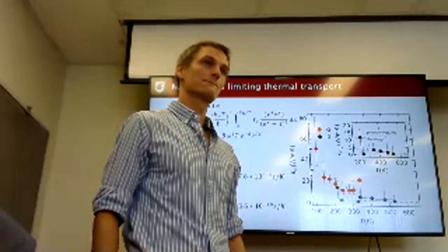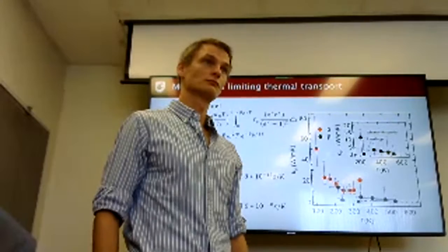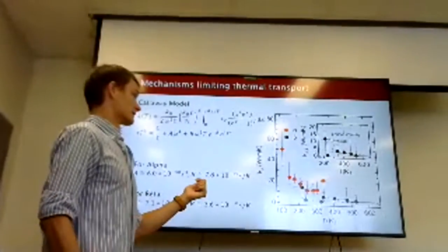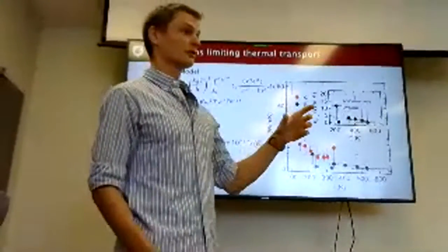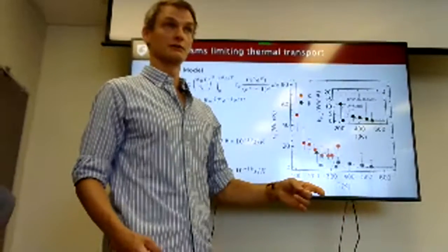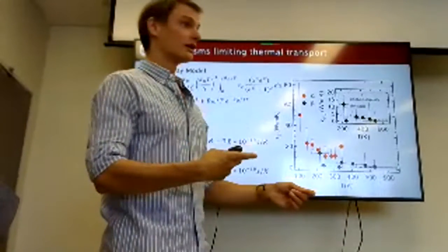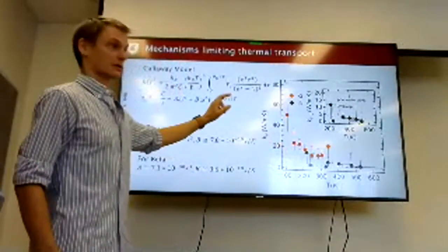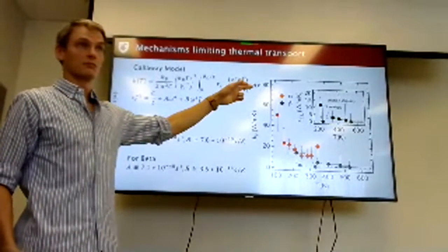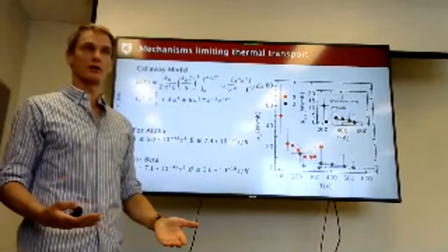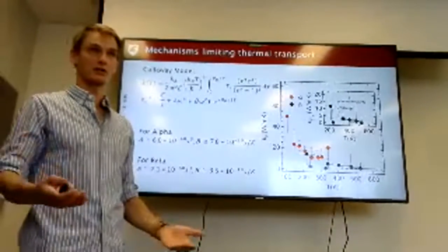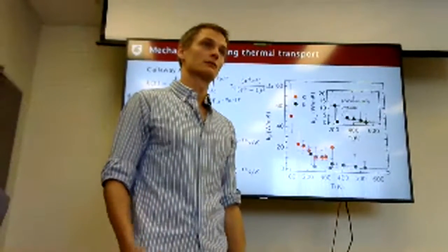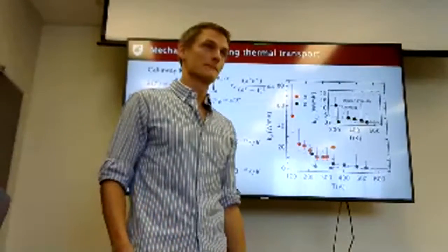But my question was, do you know what was inhibiting that thermal transport of heat? I think that's what we show here, right? I don't know just how the computers figured it out, because I can't solve those differential equations on my own. But what we see here is we can explain the low conductivity using Umklapp scattering, which is not going to happen that often because it's a multiple phonon interaction. And if that's the dominant mechanism in heat transfer, it's not going to happen very often. So the explanation was the folding. Okay.